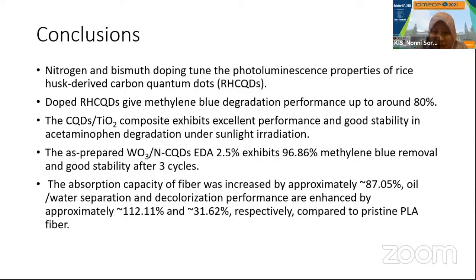and the performance of the methylene blue removal is actually better. We can reach around 97% removal, and even after we reuse it for 3 cycles, we can still achieve methylene blue removal of more than 80%.